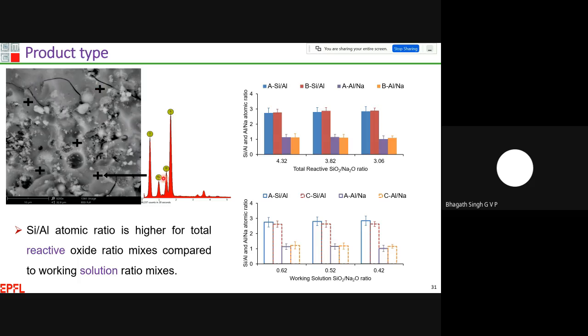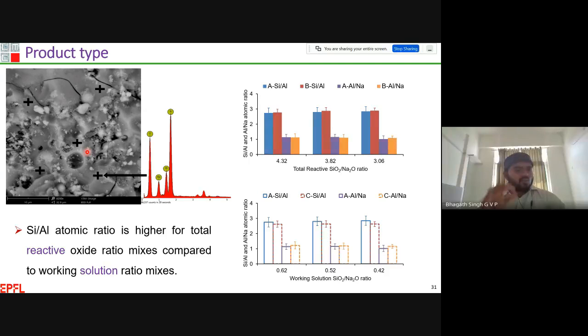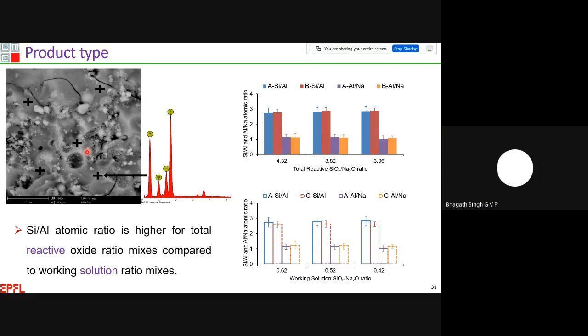Then I carried out the EDAX analysis, as you can see, at various locations. In all these locations, I can see silica, sodium, and alumina incorporated into this reaction product. Finally, I classified it as a sodium aluminosilicate gel formed during the alkali activation of low calcium siliceous fly ash. I also observed calcium incorporated in very few locations, but that is very nominal. The predominant quantities are sodium, alumina, and silica. So I can clearly illustrate that it is sodium aluminosilicate gel if you use low calcium siliceous fly ash.